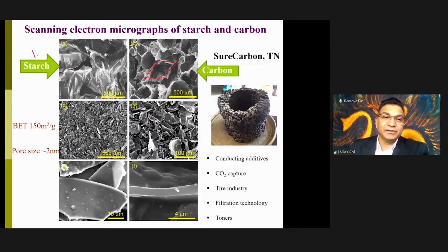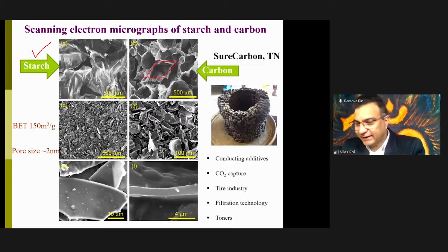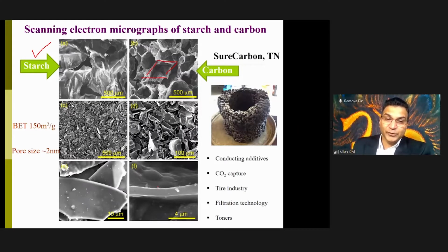As such, we took this starch-based packing peanut, and then we converted it into carbonaceous material just by heat treatment in an inert atmosphere at around 600 degrees Celsius. It produced a very unique type of carbon where the sheet diameter is up to 1 micron, and the thickness of the plate, and the width of the plate, is several microns long. Such carbon has many other applications, not only in batteries, but many others.